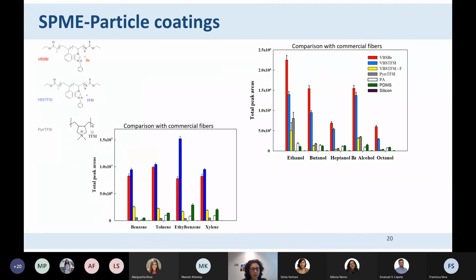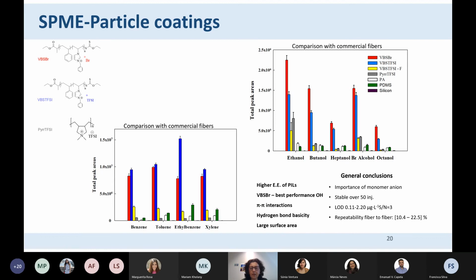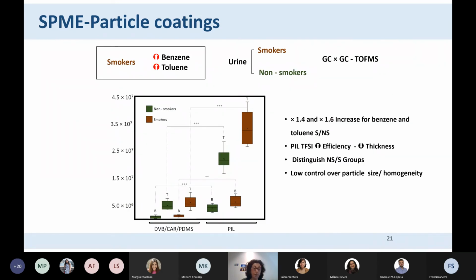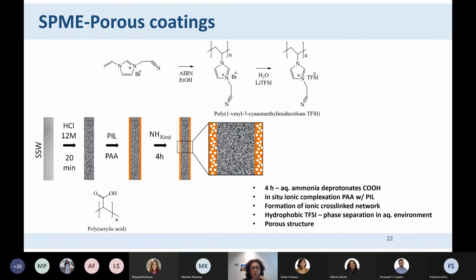And we did. We tested these samples with alcohols. And here, as you can see, we are doing quite well with alcohols. We tested them with the BTEX mixture, and we also do quite well with the BTEX mixture. But the problem with these fibers is that they were only stable over 50 injections, and the reproducibility was very low because we kept on losing particles from our fiber. So although the results are interesting, the fiber is not very stable. So I'm going to skip this, and I'm going to go to porous coatings.